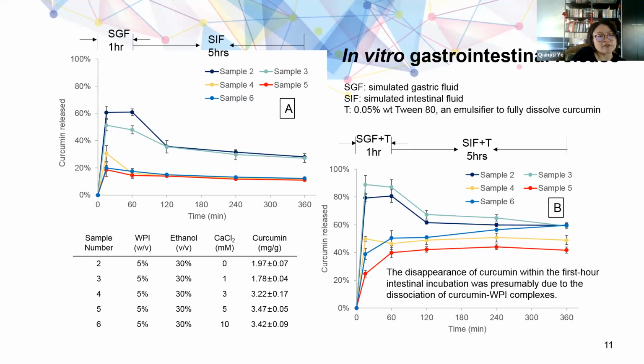Cross-linking at higher calcium ion concentrations brought it back to be gastro-resistant, exhibiting sustained and intestine-targeted release characteristics observed in samples 4 to 6. The disappearance percentage of curcumin within the first hour of intestine incubation in sample 2 was more than 20%. It was much higher than its degradation result in the previous stability test under the same condition, which was about 10%. To investigate these differences,